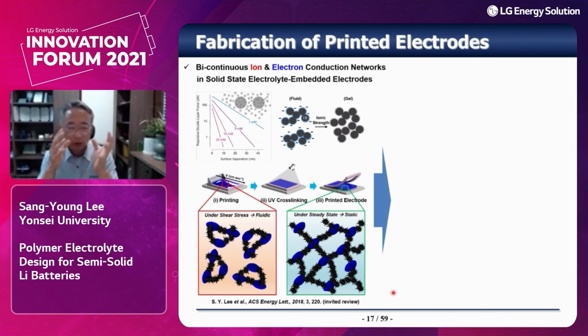So when we fabricated the solid-state electrode, including the sulfide or the oxide embedded electrode, our attention should be paid to how to ensure the bicontinuous ion and electron conduction networks. That's a very critical challenge we need to overcome. So here we have exploited a new concept, ionic strength control. By exploiting this concept, we can elaborately adjust the dispersion state of the electrode active materials in addition to the carbon blacks.